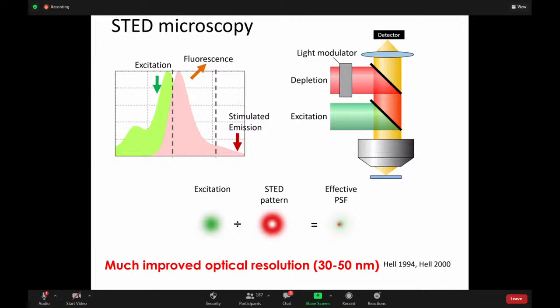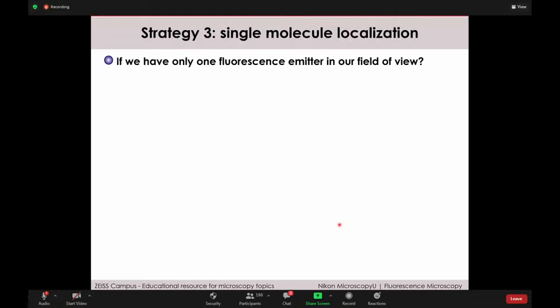Now once you overlap these two beams, you are effectively collecting the fluorescence only from a very small region. That gives you a much improved resolution, and you can get an optical resolution of 30 to 50 nanometers. But it has also been improved much, much higher, right? Utilizing this sort of STED beam pattern.